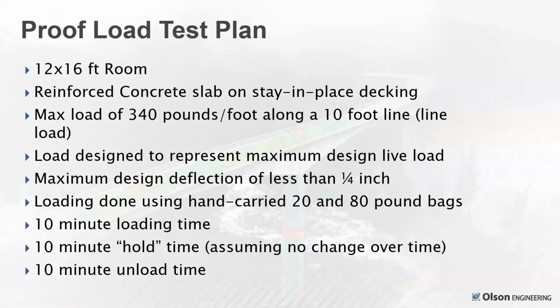So the room was about 12 by 16 feet. They wanted to see what 340 pounds per foot did along a 10-foot line, a lineal line, a line load. That was designed to represent the maximum design live load. And they wanted to see a deflection of less than a quarter inch. The loading was done with hand carried 20 and 80 pound bags to meet that exactly. 10-minute loading time, 10-minute hold time with no change over that time, and a 10-minute unload time. So very quick proof load.